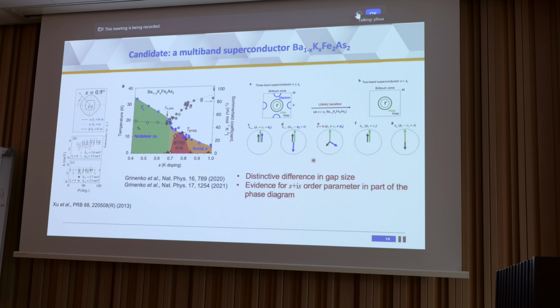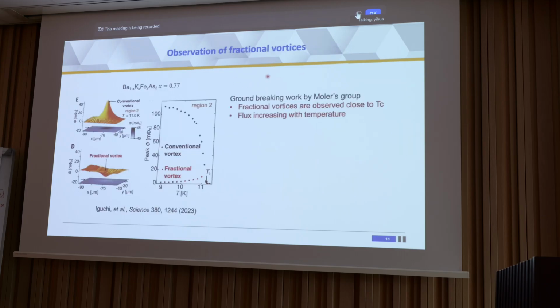Through this s plus is order parameter, breaking time reversal symmetry, we can possibly realize fractional vortices there. And indeed, as you may have heard from Yusuke, Ken Moler's group from Stanford in 2023 observed fractional vortices in this BKFA system when the doping is 0.77. The key thing they found is that besides the conventional vortices, they find vortices which have a much smaller contrast, and the integral of the flux around the vortex core is much less than for a conventional vortex. The total flux increases with temperature until the temperature reaches Tc.